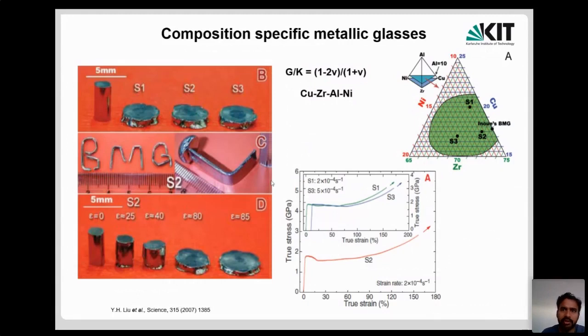And the next one is a composition specific glass. This is somewhat debatable concept because in the next slide, I'll show another group which actually counters this point. The idea of this composition specific glass is that, I don't know how many of you do mechanical behavior, but if you take the shear modulus and the bulk modulus values, you say (1 minus 2 nu) by (1 plus nu), this is the Poisson's ratio. If the Poisson's ratio is high, then this value is low and G is low. So you have the shear modulus very low. When the shear modulus is low, you can actually deform the material much more easily.